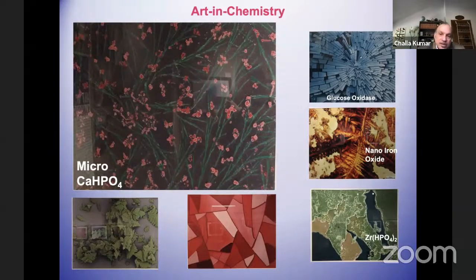If you put a protective layer, they will last longer, right? Because we want to have 20,000 hours, not 90 hours, for the half-life. You can definitely make it because you protect it from oxygen, and then the degradation pathways are reduced dramatically. And then you look for chemical reactions between the excited states and the matrix. The sites that are likely to quench the excited states or react chemically are disulfide bonds. So what you do is undo the disulfide bonds and oxidize them to sulfonic acids. Then they will no longer be degradation pathways. So you can systematically shut off each degradation path.